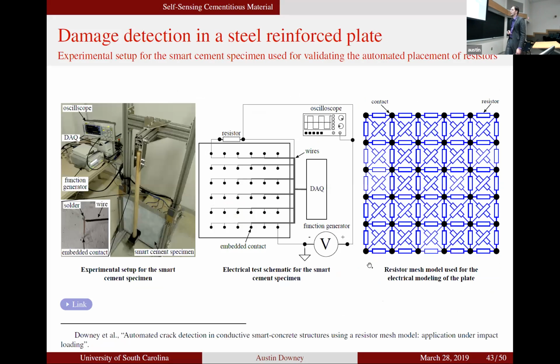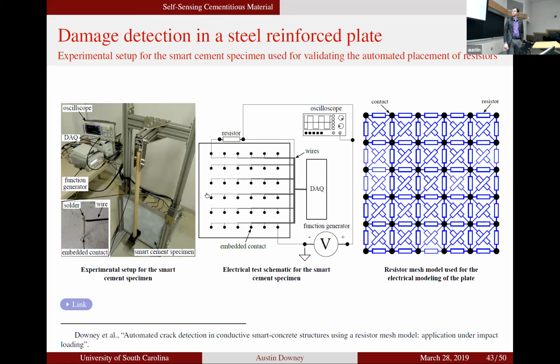But we want to do this automatically. And so we went back and thought about this again, and how can we automatically place damage resistors into a mesh. So we need a data set that continuously grows, and to do that, we took this concrete plate. So this is a 0.5 meter by 0.5 meter concrete plate filled with multi-walled carbon nanotubes, and we repeatedly impacted the plate. Again and again and again. Here's our experimental setup, and then here's our resistor mesh model.